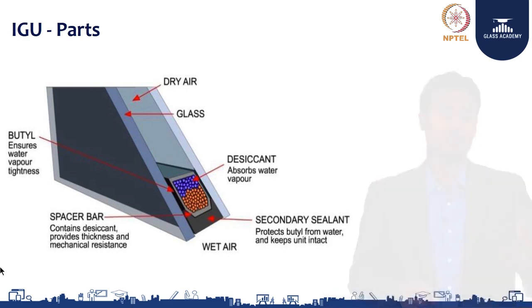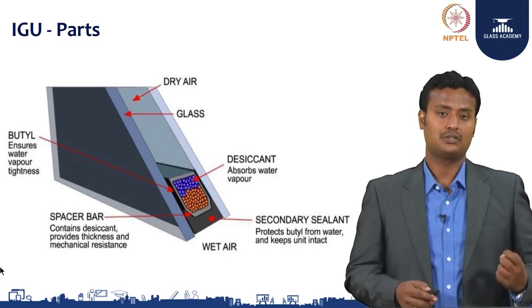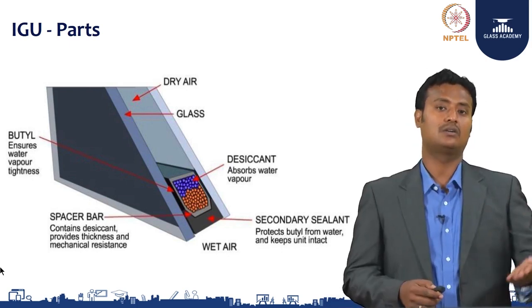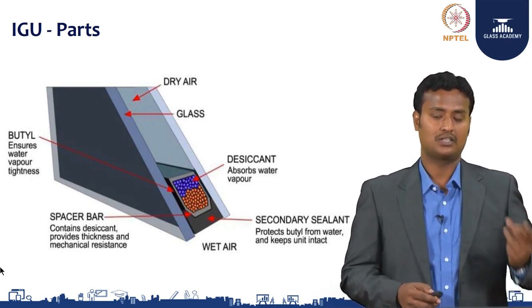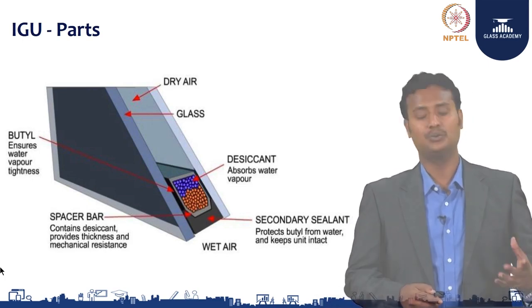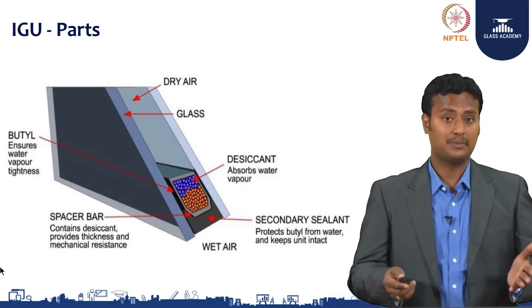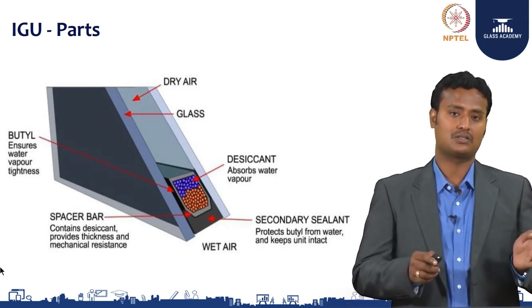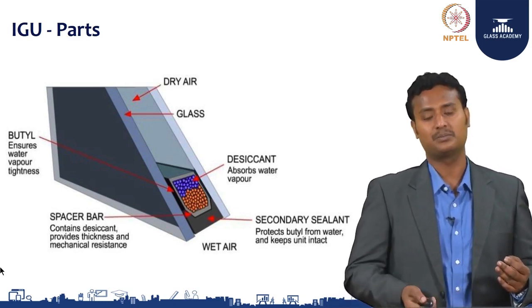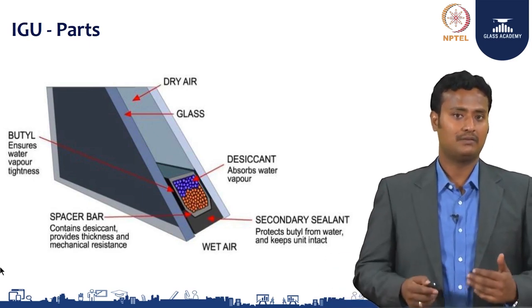If the IGU needs to prevent condensation, the desiccant must be a proper one. The desiccant absorbs water moisture present in the IGU or anything that comes inside — it absorbs water moisture or hydrocarbons. It should not absorb thermal performance gases like argon or noble gases such as krypton. The space between the two glasses can be kept as vacuum, dry air, or filled with argon, xenon, or krypton gas, depending on the performance you want.